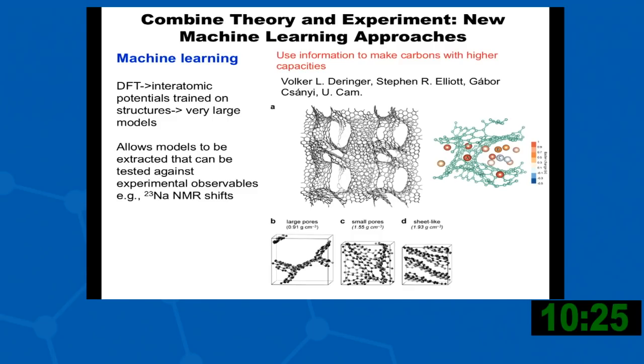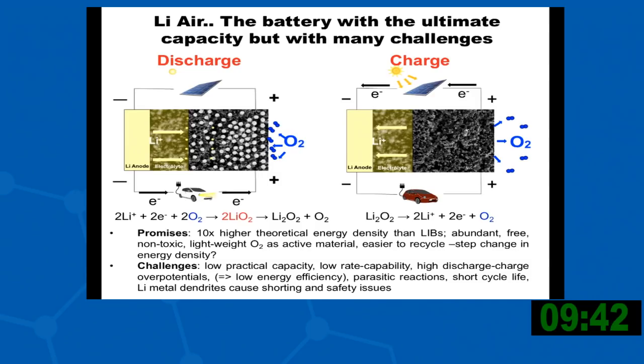So where are we going next? I'm working with my colleagues Gabor Csányi and Volker Deringer and Stephen Elliott to try and use machine learning approaches to develop structures of new carbons. And what we do is we derive DFT structures of smaller fragments, and then we train it to generate new interatomic potentials, which allow us to get very large carbon structures. And the reason we do this is we can then capture various parameters that we can measure experimentally, and the specific experimental parameter that I'm interested in is the sodium NMR shift, to try and correlate our NMR spectroscopy with the types of carbon fragments, and particularly the types of defects that form in these systems.